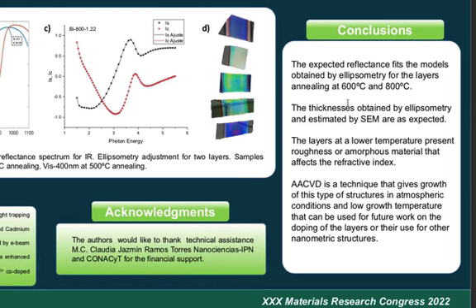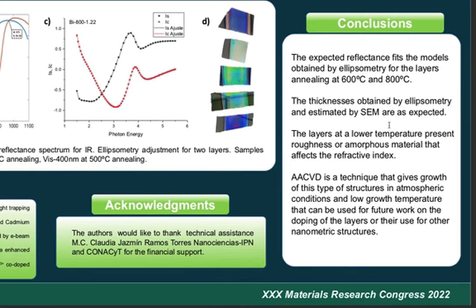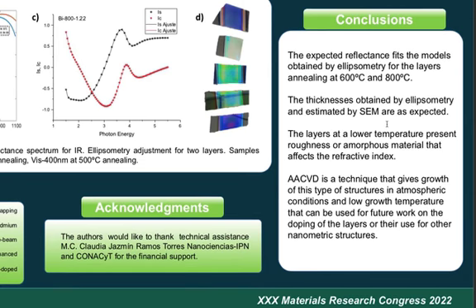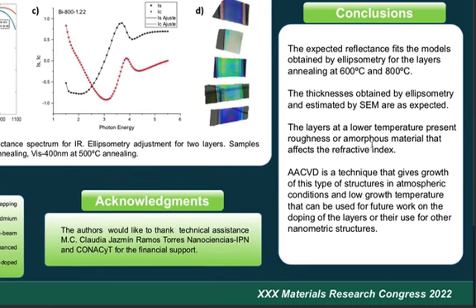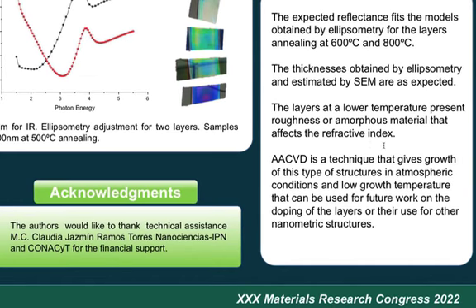Conclusions. The expected reflectance fits the model obtained by ellipsometry for the layers at 600 and 800 degrees. The thickness obtained by ellipsometry and estimated by SEM are as expected. The layer at lower temperature presents roughness or amorphous material that affects the refractive index. AACVD is a technique that gives growth of this type of structures in atmospheric conditions under low temperature, that can be used for future works in the doping of the layer or for the use of other nanometric structures.